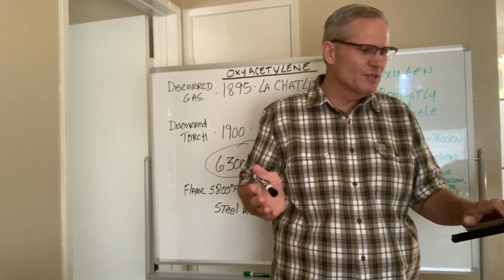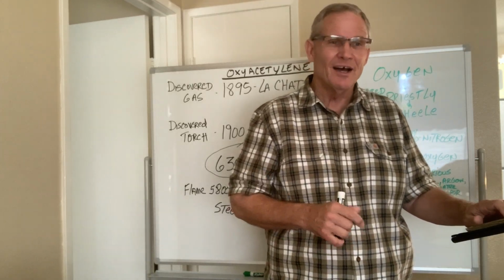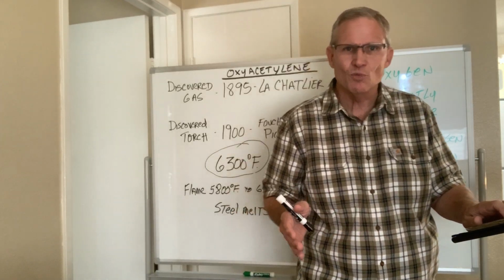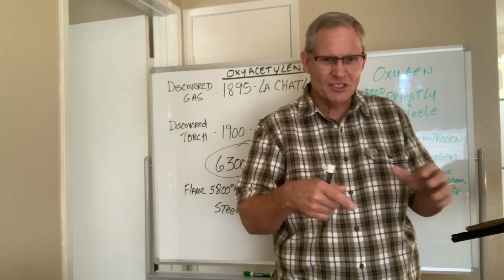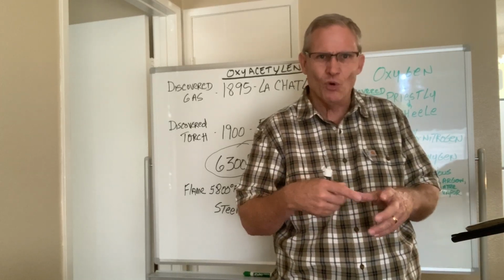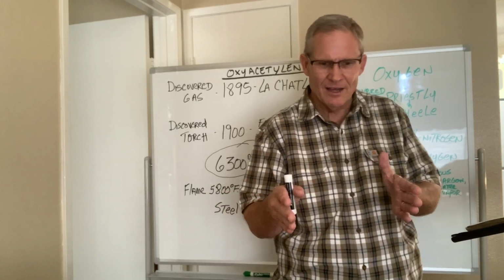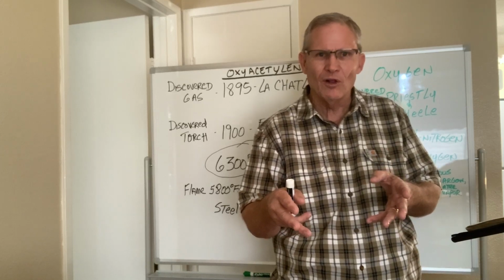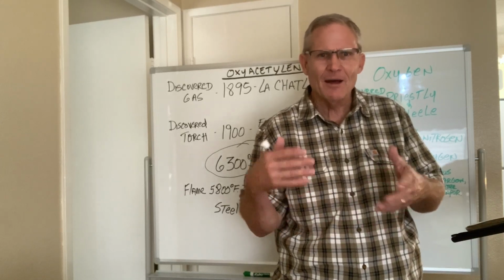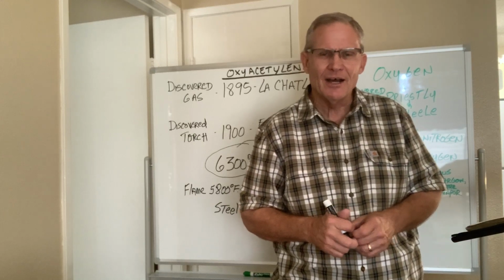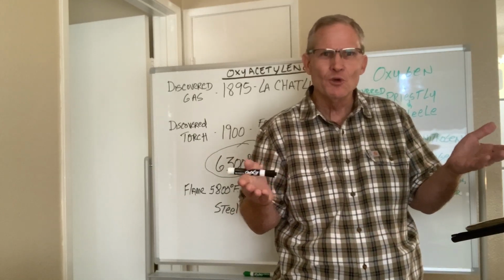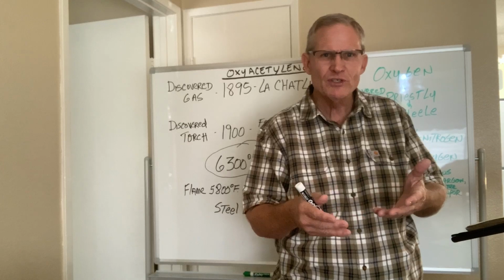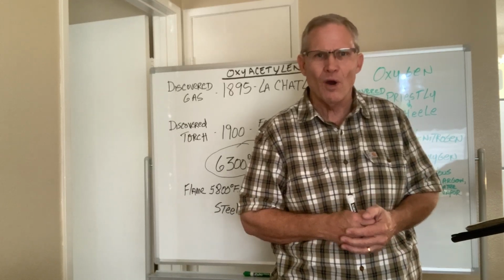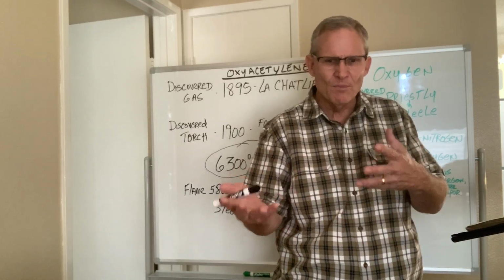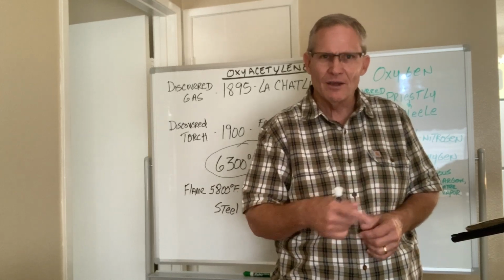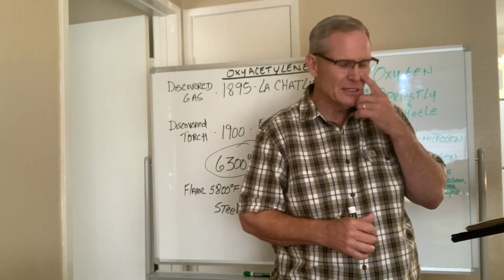So the other thing that we use it for is eliminating moisture. When I was on high-rise buildings and I was welding, we would take the oxyacetylene cutting torch and we would heat the weldment up that I was going to weld. It had some moisture, so you'd have some dew point in the morning. So there'd be some moisture on the weld. You don't want to weld over water. So we would heat it up, remove the moisture, and then actually start the welding process itself.